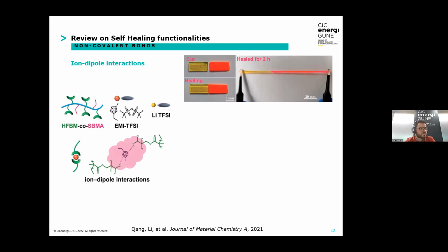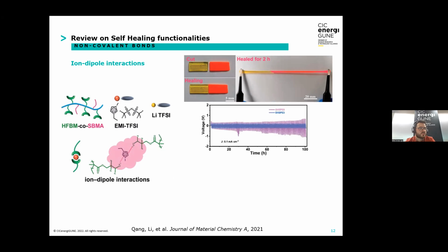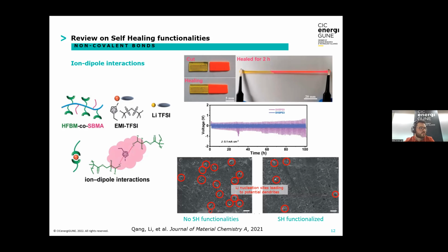In terms of electrochemistry, the membrane containing self-healing functionalities, as in the previous case, offers a much lower lithium stripping and plating overpotential. And going again back to the scanning electron microscopy images, the electrolyte with no self-healing functionalities has many more lithium agglomerates on the surface that can lead to potential dendrite formation, whereas the self-healing functionalized polymer electrolyte leads to a smaller amount of lithium agglomerates or dead lithium formation, which can lead to nucleation sites for potential dendrites.